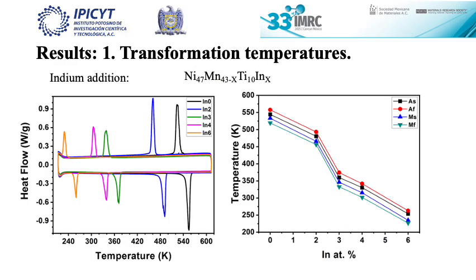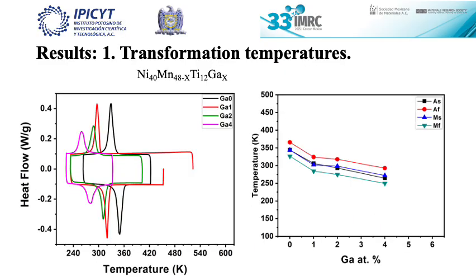For the transformation temperatures in the case of indium addition, we can see an important decrease of temperatures of transition. At the right side, we can see the characteristic temperatures as they decrease with the indium atomic percent. Also, for the case of gallium, we can appreciate a decrease of transformation temperatures.